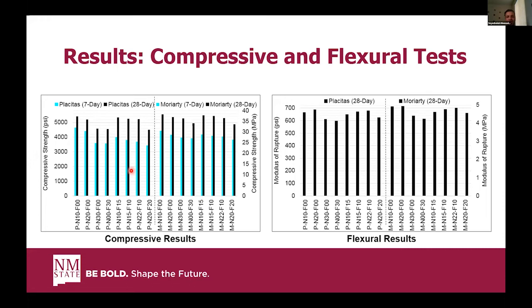As I've already mentioned, for the compressive results in the left figure, we can see that with increasing the natural pozzolan, the compressive strength decreased for both types of the aggregates. But the more important point here is that the compressive strength of mixtures with 30% fly ash was really close to the mixtures with 30% natural pozzolan. And in the flexural results, in the right figure, we can see that only one mixture's modulus of rupture was slightly less than 600 psi, but was really marginal. And all remaining mixtures were more than 600 psi, which is acceptable to many transportation agencies for both types of the aggregates. So again, we can suggest that this natural pozzolan, pumicite, can be a good alternative to fly ash in terms of both compressive and flexural tests.